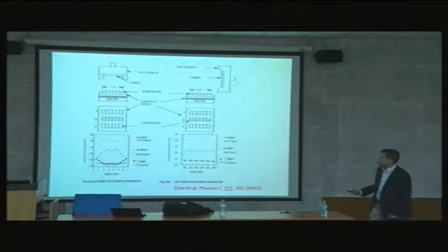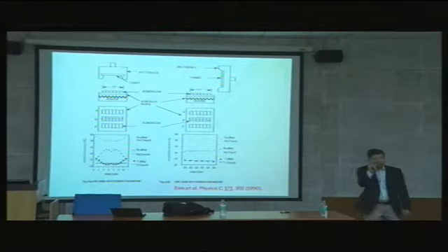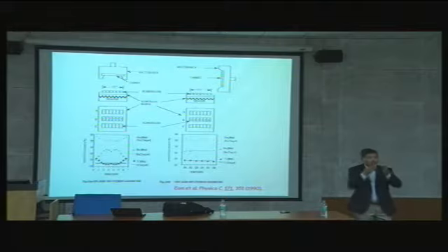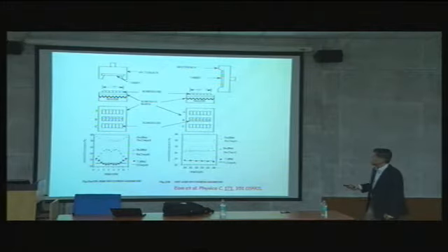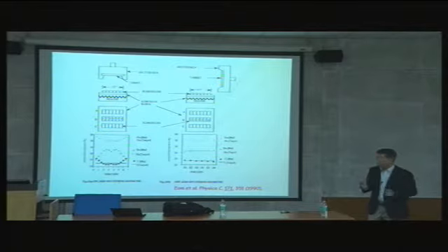The problem is that the particles coming from the erosion area of your target form a ring-shaped pattern, and that region has the highest negative ion flux. Whenever you hit the highest negative ion region, you get the most serious negative ion bombardment. So the non-uniformity comes from which region has more negative ions. Not only non-uniformity, it also shifts the composition a lot. That's why there's a lot of struggle.